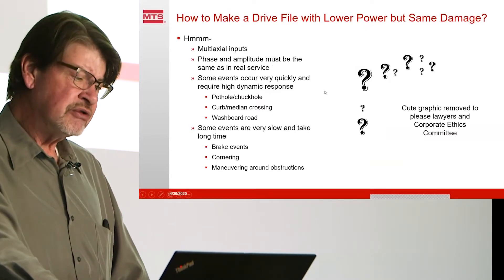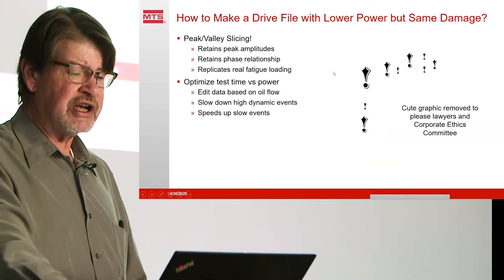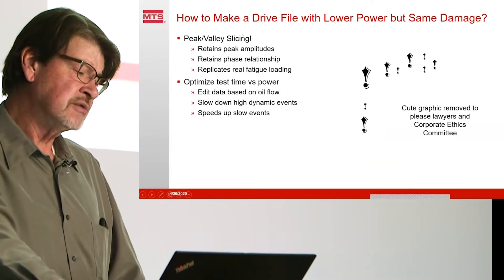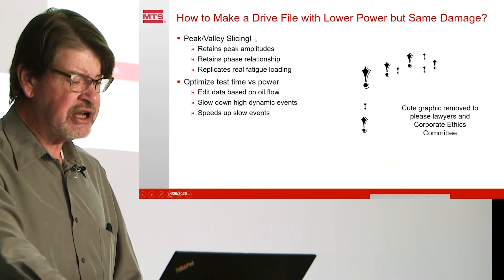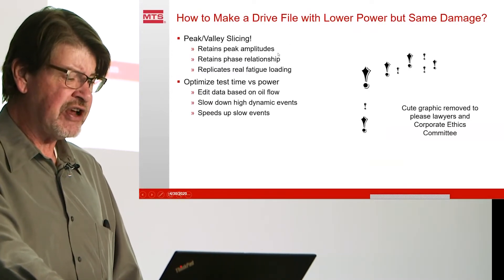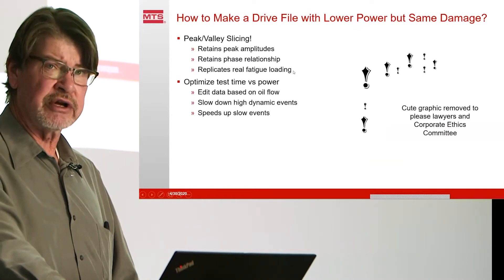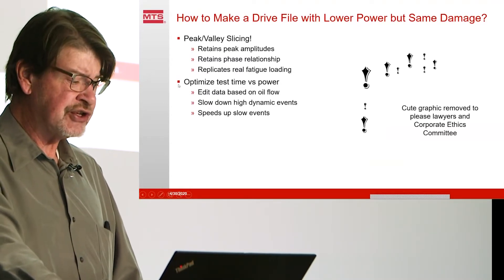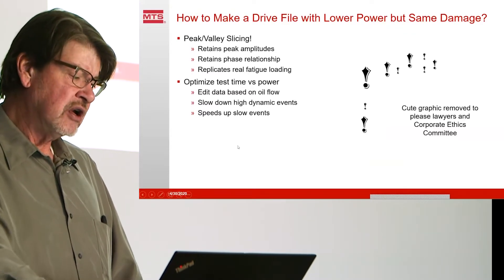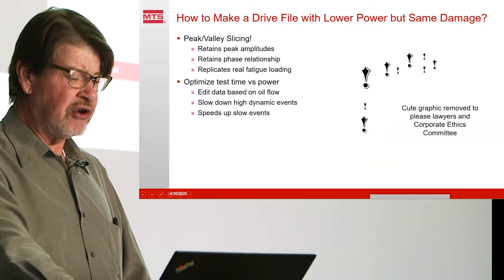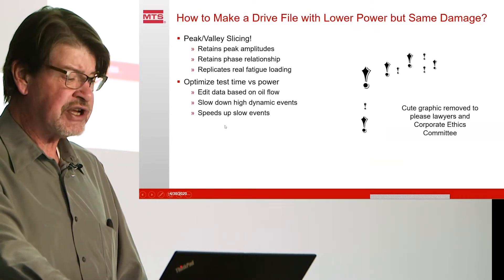So how can we get this damage content contained within our test and still reduce our power demand? One way to do that is with peak valley slicing. It retains the peak amplitudes, retains the phase relationship, and can replicate real-time fatigue loading in a multi-axial system. It allows us to optimize test time versus power. We can edit the data based on oil flow — slow down high dynamic events and speed up slow events to reduce test time.